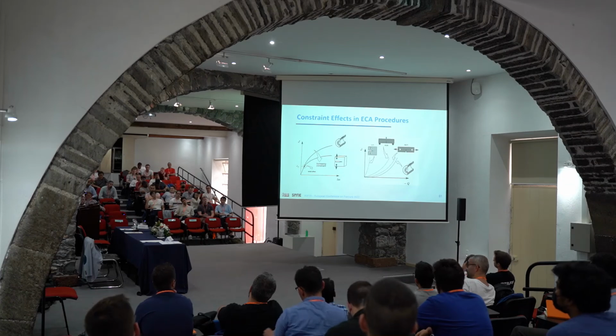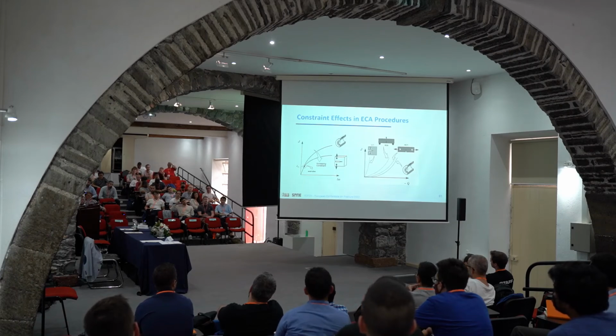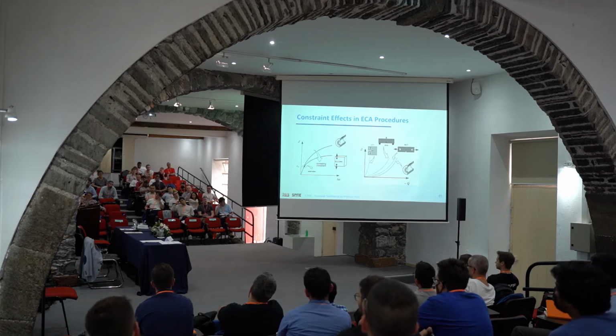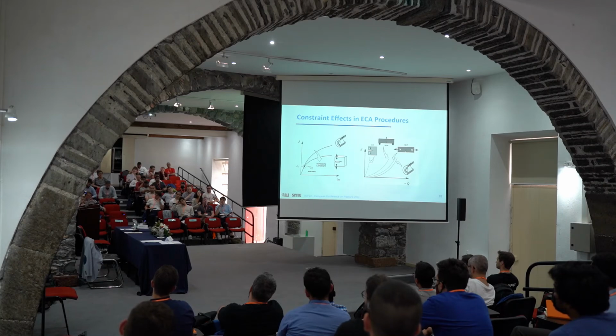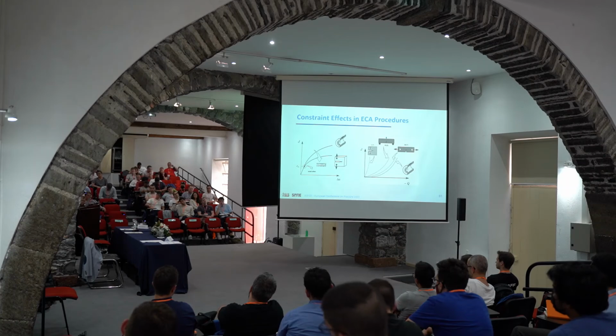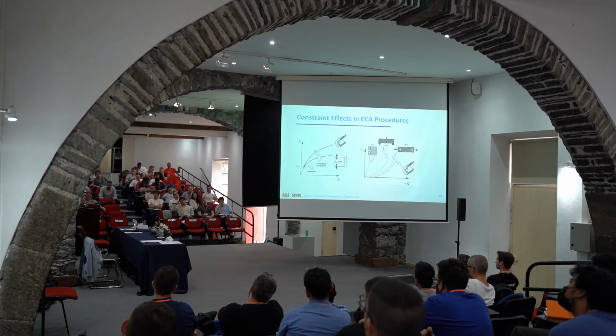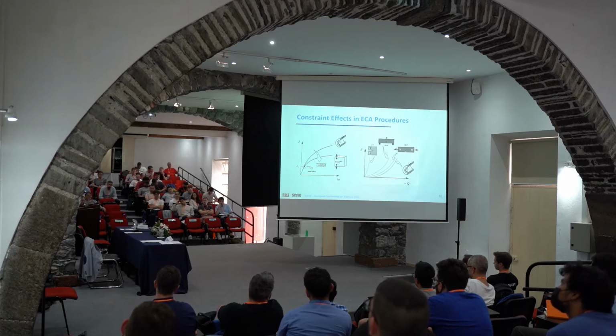Look at the pipe. You see, the J-Q trajectory is far away from the CT. That means that the pipe is much less severe than the CT specimen. What's the meaning of this? Again, close to your question. If I use a CT specimen to design the launching of my pipeline, I'm going to be very, very conservative. And the problem here is not a matter of being conservative. The problem is you are doing this on a ship. You don't have time to do all the repairing. It's like those movies when you are in a space station and there is something broken outside and the guy goes down there.